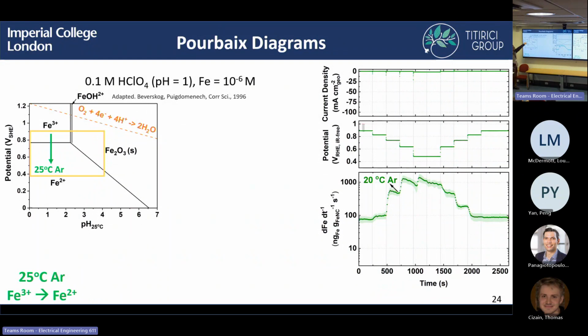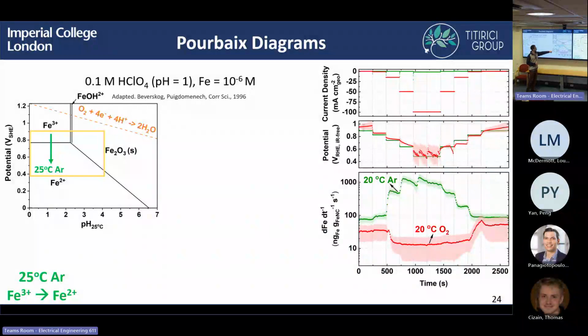And just to say here, this is a Pourbaix diagram taken from literature at 25 degrees. And we're looking here at pH 1 because we're using 0.1 molar perchloric acid. So then we look again at the 20 degrees measurement in oxygen, where we see as we step down in potential, the iron concentration actually decreased once we hit minus 15 milliamp per centimeter squared.